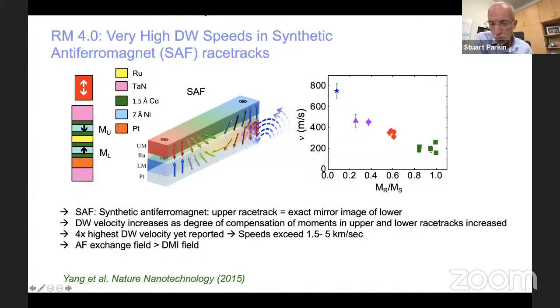And so, as I said, you could use something called oscillatory interlayer coupling that I discovered many years ago. And shown here in this cartoon, this yellow layer is a thin layer of ruthenium, which essentially is used to couple two racetracks above and below, shown as this blue-green layer, which is cobalt, nickel, cobalt. And the two moments can be coupled antiferromagnetically, as shown in the cartoon. And in fact, you can obtain a mirror image of whatever is the magnetic profile of one racetrack in the opposing racetrack. And by suitably designing these two layers, you can essentially eliminate all the moments. So the net moment in this synthetic antiferromagnetic racetrack goes to zero. Nevertheless, of course, locally, there's magnetization.